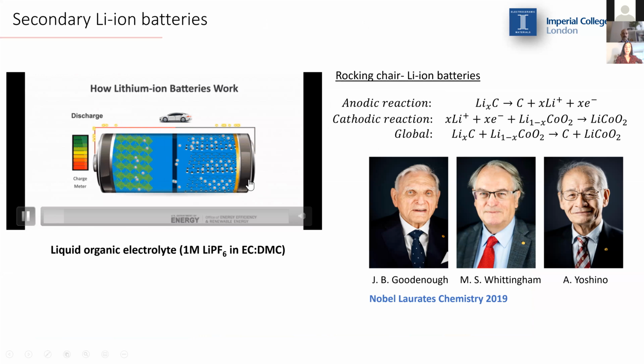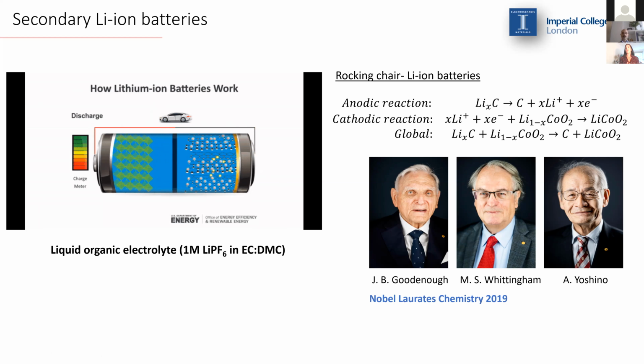During the discharge, the lithium ions deintercalate from the anode and intercalate into the cathode, and the electrons flow in the same direction. And during the charge, the lithium ions deintercalate from the cathode and intercalate back into the anode. In commercial batteries, the anode is graphite and the cathode is a transition metal oxide, a layered oxide, typically lithium cobaltite.